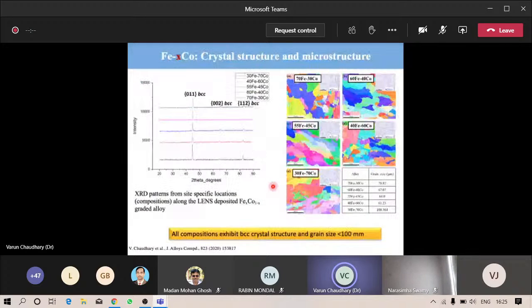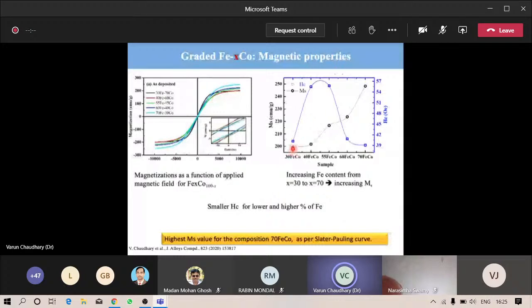Then we come to the iron-cobalt system. Here the crystal structure for all these compositions, changing from iron 30 to iron 70, is body-centered cubic, and the grain size is equal to or less than 100 nanometers. For the magnetic properties, the saturation magnetization increases with increasing iron content. However, the coercivity first increases and then decreases. From here, we can conclude that this particular composition has high saturation magnetization and a low value of coercivity.